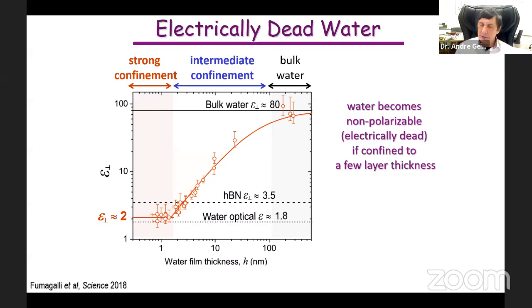It has implications for many fields, like the double layer in capacitors, like proteins, because our bodies are 80% water, and our bodies are protein machines, and how those protein machines work relies on properties of water, and trying to understand those properties. Usually people assume water is an isotropic medium with bulk properties. In fact, when you are talking about this nanoscale, it is no longer isotropic. It loses its electric polarizability, at least in one direction.